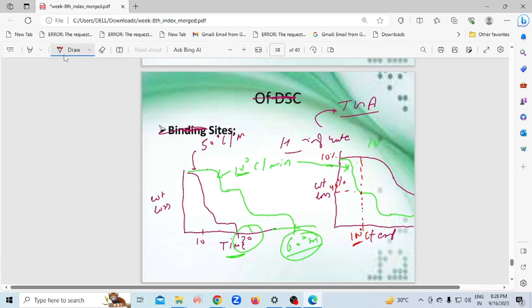At 100 degree temperature, the material is 40% decomposed at the low heating rate, but at the higher heating rate, at 100 degree temperature, only 10% is consumed. That's why it should also be optimized. You need to fix the heating rate where you are able to find a sharp decrease like that. You need to find this type of sharp decrease of your sample. So this is the effect of heating rate.